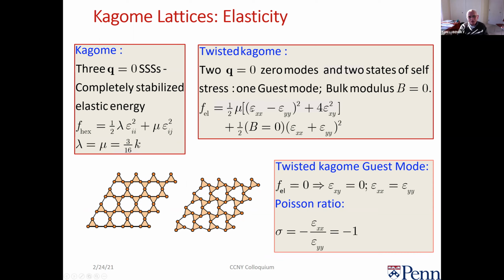And so for the energy, I have two shear modes which cost energy, and a bulk mode which doesn't. If I look at the elastic energy of the system, and I take epsilon xy equal to zero and epsilon xx equal to epsilon yy, that would give me a zero energy state, which we know we have. And that gives me a ratio of strain along the x direction to strain along the y direction which is minus one. So that gives you a negative Poisson ratio, which is exactly what you get when you have a system which has a vanishing bulk modulus.